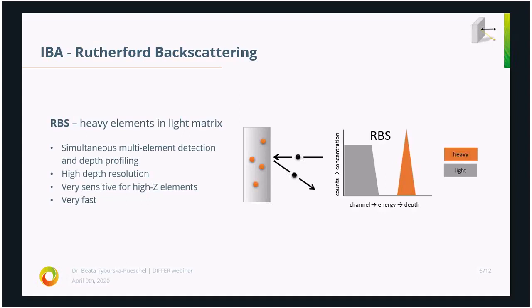It has a very high depth resolution, even down to 5 nanometers. It is very sensitive, especially for high Z elements. Within 5 minutes, you can have millions of counts from high Z elements, so therefore you can go to low ppm detection levels for those elements.